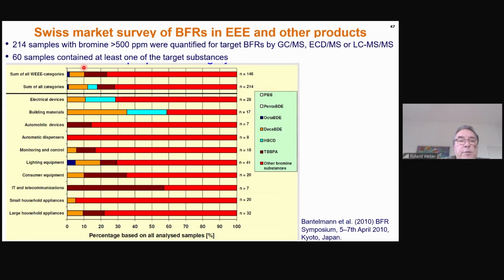So here you see more detail of the results. 60 samples contained at least one of the target substances. And here just a little bit of detail. When you look at building materials, you see that in 2008, still a considerable share of the building materials screened, it were only 17 samples, but still around 30% contained DecaBDE. But the electrical devices, already only 10% contained PBDEs. For the automotive devices, it was only 7 samples, and none of them contained PBDEs.